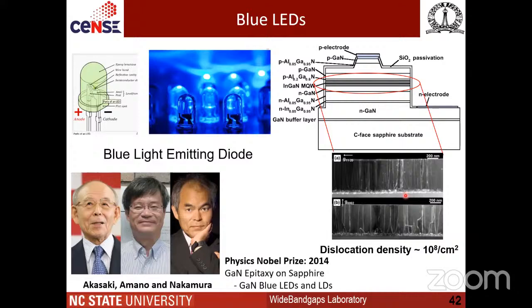Remember, I talked about dislocations, one-dimensional defects that one material can have. And these materials are actually full of dislocations with such a large density. We have 10 to the 8 dislocation defects per centimeter square. But these materials magically work despite the fact that you have so many dislocations. And the physics behind it was only resolved a couple of years back, and it was a mystery to understand how these light emitting diodes work so efficiently.